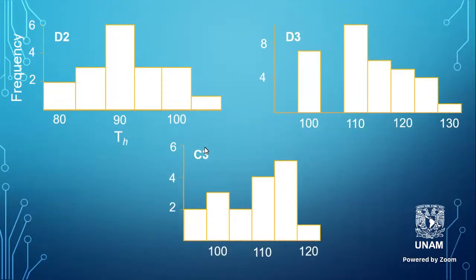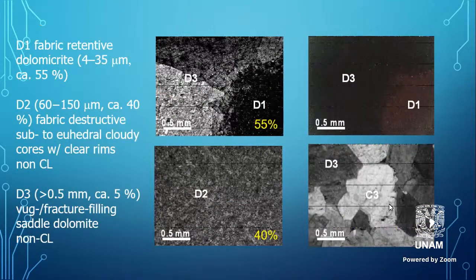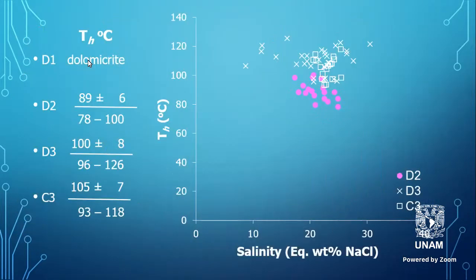We looked at the fluid inclusions, and we always express the homogenization temperature in histograms. These are the homogenization temperatures of the two-phase primary fluid inclusions in D2, D3, and also in C3, because there was a late generation of calcite cement, C3, that came after D3. I summarized the homogenization temperature in D2, D3, and C3, the mean value plus or minus the standard deviation, and below is the range: 78 to 100 degrees Celsius here, 96 to 126 here, and 93 to 118 here.